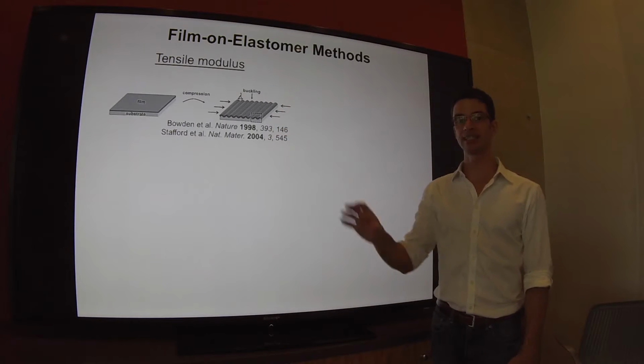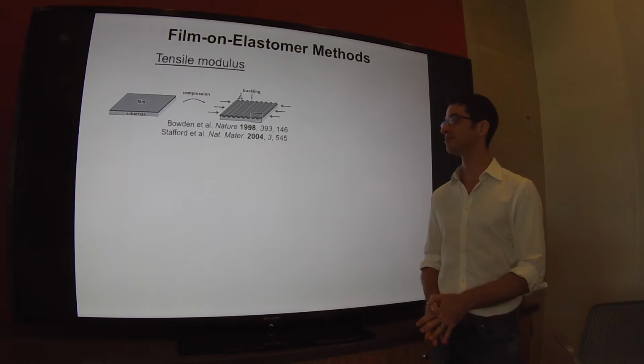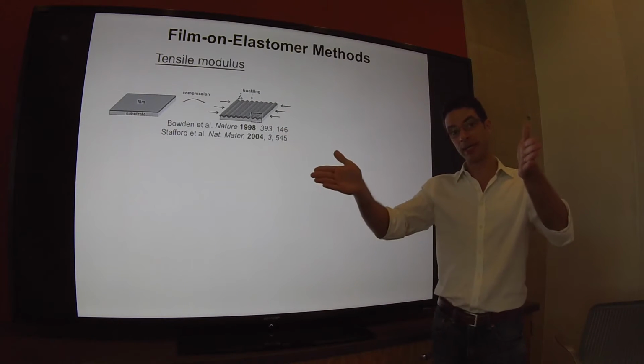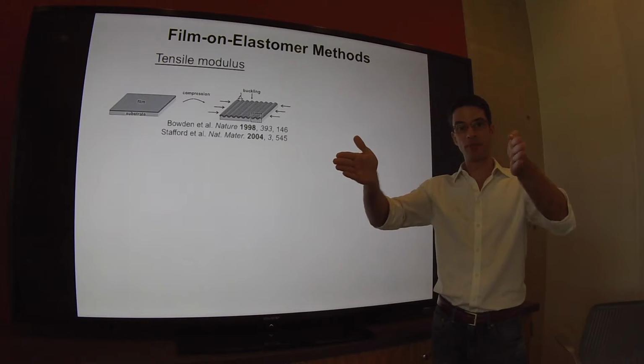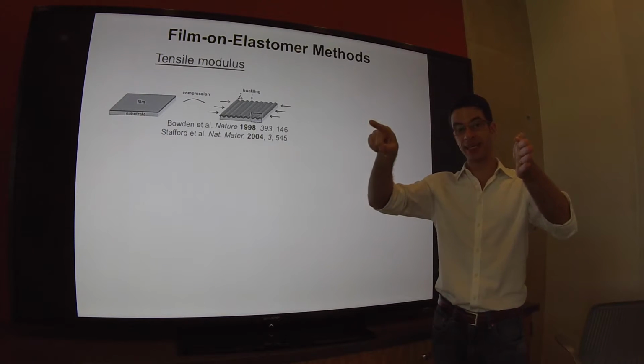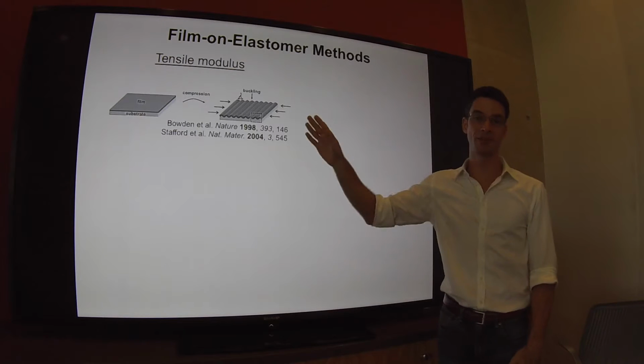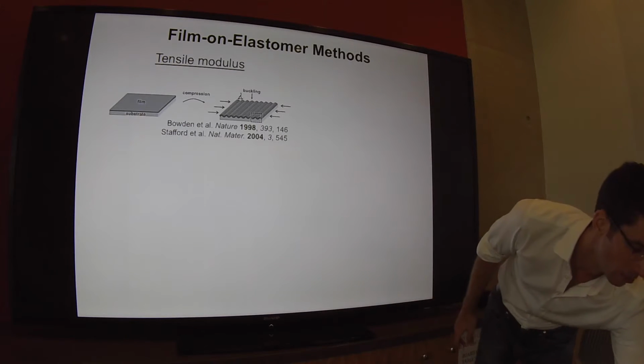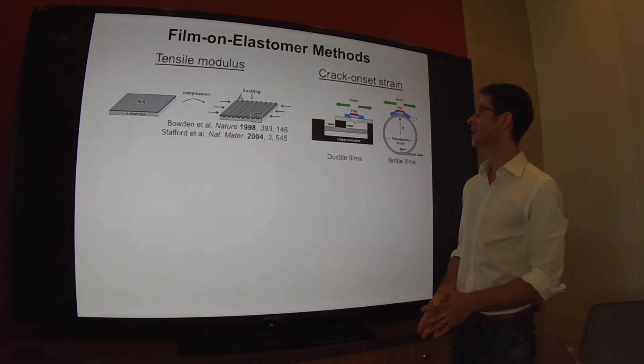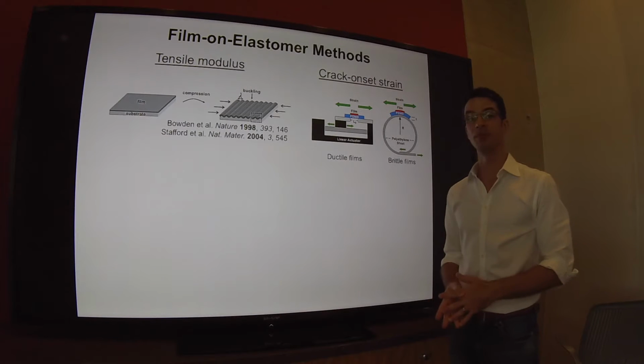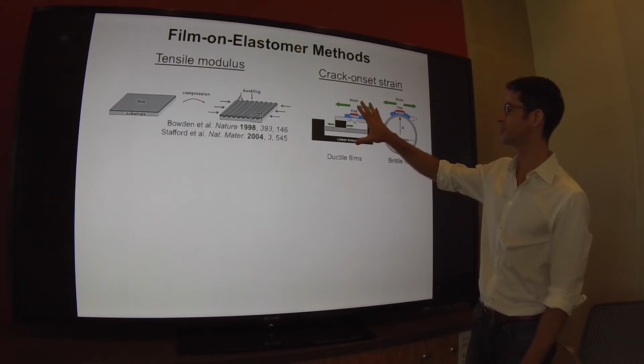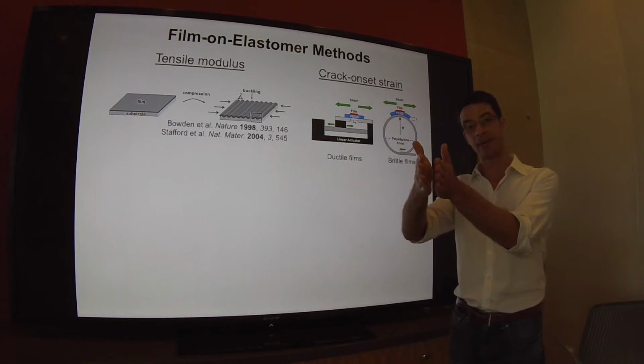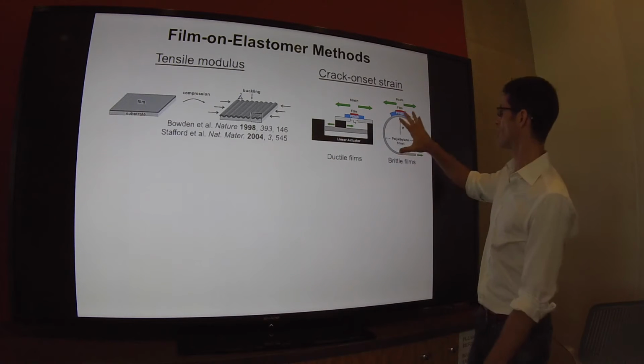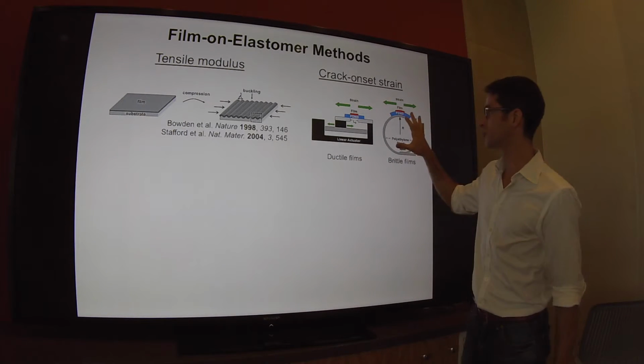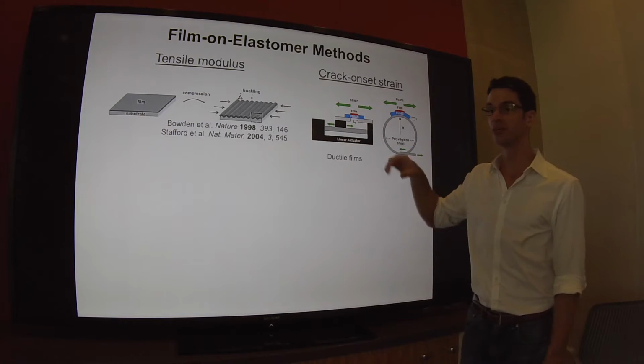So we can measure the tensile modulus using this film-on-elastomer method, where one compresses the film under a small tensile strain and converts the buckling wavelength and the film thickness into the tensile modulus. You can get the crack onset strain, which is a measure of the brittleness, by putting the film either on a linear actuator or on a bendable substrate for a low strain regime and the high strain regime.